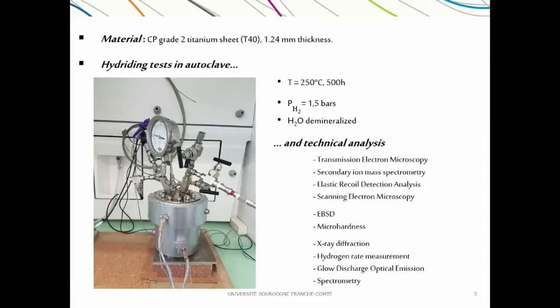After these treatments, we carried out hydrogen tests in an autoclave located at ISITE-BFC, in this condition of temperature, pressure, and solution. We use different technical analyses, such as EBSD, X-ray diffraction, and transmission electron microscopy, to characterize the samples before and after each treatment.